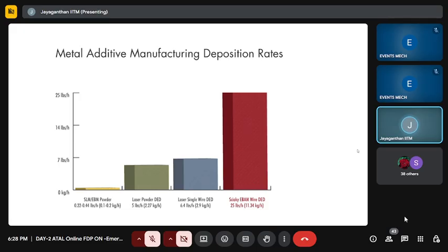That's why I'm trying to highlight from extreme left to extreme right. We have wire-based direct energy deposition, powder-based direct energy deposition also. You can see laser powder DED 2.27 kg per hour. And if you look at the extreme left, 0.1 to 0.2 kg per hour. For example, if you want to do weld repair, which one will you use? Having listened to my input, if I ask you, you want to do weld repair, a lot of components in aerostructure also, they don't want to just dump immediately. Non-critical parts, they want to repair actually.